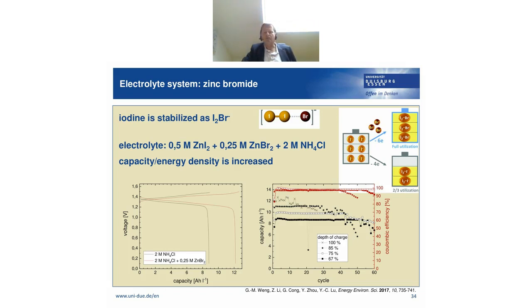So our electrolyte then is composed, for example, of zinc iodide, of zinc bromide, and of ammonium chloride. Like this, the capacity, or you can say the energy density, is increased, which is shown here in the voltage capacity curve on the left. We have here the red discharge curve, for example, where we have a capacity of 12 amp hours per liter upon adding zinc bromide, and without zinc bromide we have here around 9 amp hours per liter.